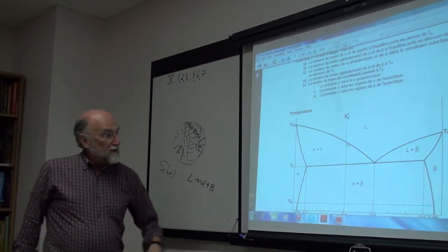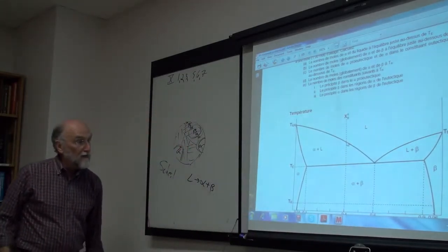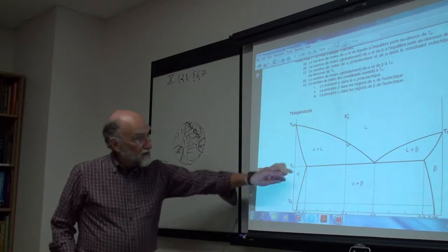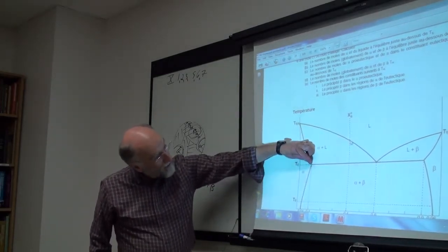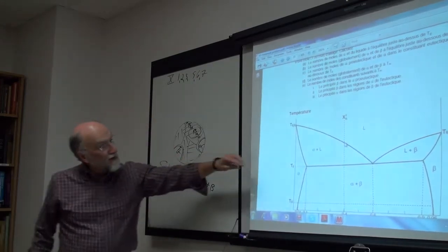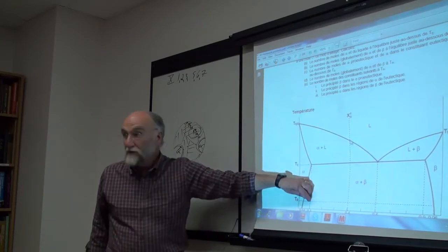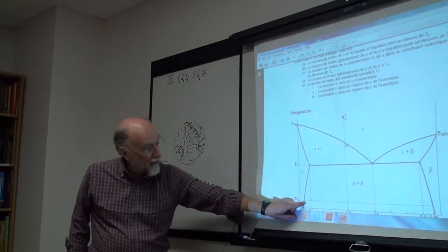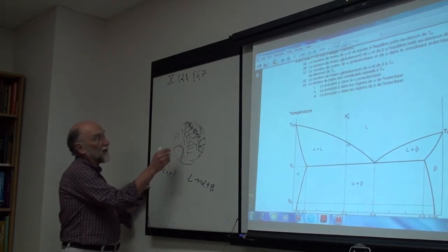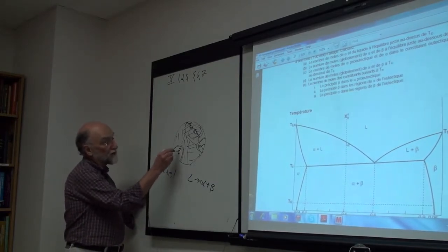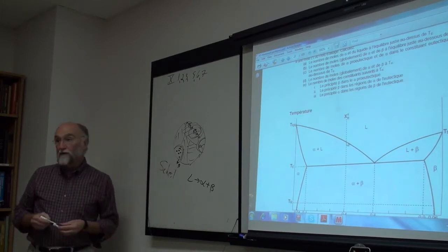But if you cool it very slowly, or you cool it down to TR and then anneal it for a long time, what's going to happen now is, of course, the grains of alpha are now supersaturated. The grain of alpha here, the alpha primary, overall composition is here, but when you cool it down, you're now in the two-phase region. The alpha has only this composition. So within a grain of alpha, you're going to have small precipitates of beta forming within the grain of alpha.